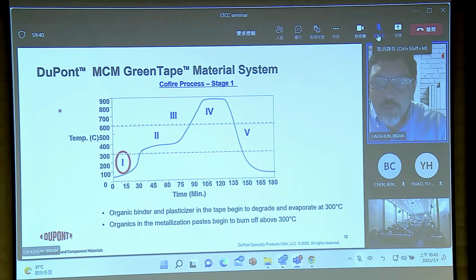So to go through what a typical firing profile is, and you'll see this over the next couple slides, usually you put it in either a box furnace or a belt, you start at low temperature, and in the beginning parts of firing, you're going to heat relatively slow up to a shelf. And that's really to do all the pyrolysis and decomposition of the resins and to get all of those out of the system. Not only do you need to reach high enough temperature to decompose the resins, but you also, on a thick part, have to diffuse out those volatile decomposition products, water, CO2, CO, those kind of things, which may need to travel millimeters through a part on the interior. And so that's why we have a shelf there.